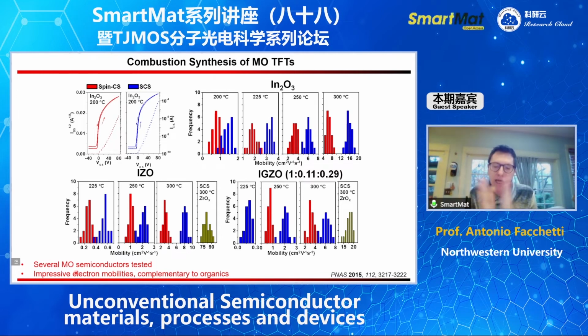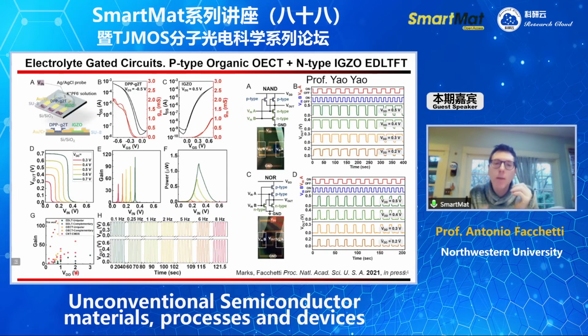So the question we asked ourselves: can we combine them, particularly if you want to make electrolyte-gated circuits? If you look at the literature, particularly for N-type electrochemical transistors, this is still very lacking. So our idea was to use electrolyte gating and use a P-type organic functioning as an organic electrochemical transistor. I want to remind you, electrochemical transistor means the ions have to penetrate into the semiconductor. And then I use an N-type indium gallium zinc oxide metal oxide functioning instead as an electrical double layer TFT. Here you have only ions which stop at the interface with your semiconductor, and you have a formation of an electrical double layer.